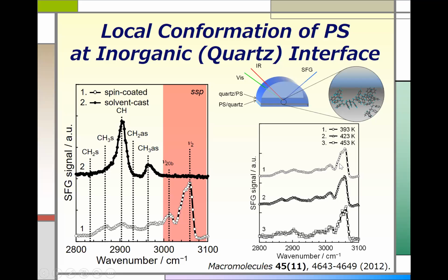but these peaks could not disappear. What this means is that polymer chains at the substrate could not be relaxed. So imagine the following. You have polymers, and if those polymer chains are attached to the solid substrate, then polymer chains could not be moved. That's what I'm talking about. That is why composite materials could play an important role for many industries.